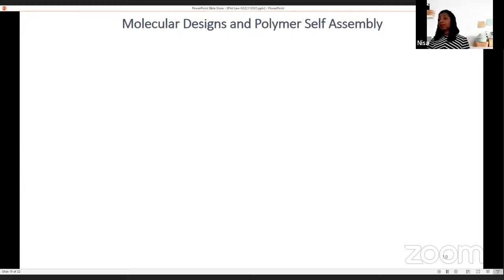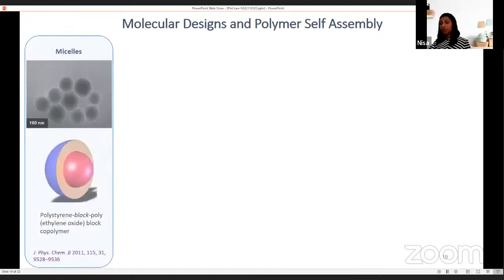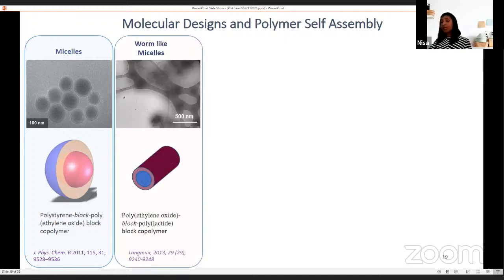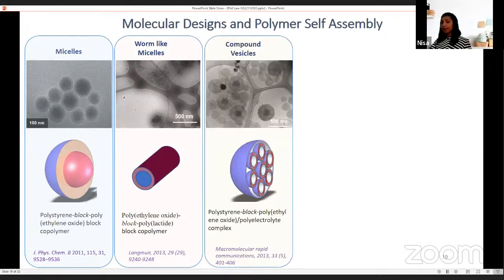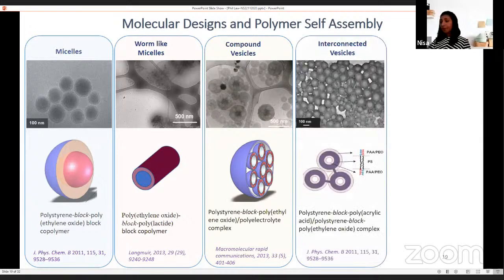I'm going to show you some examples of nanostructures we created in our research using block polymer self-assembly. These are spherical structures formed from a diblock polymer. Here the polystyrene chains form the core and PEO forms the shell. In this study, we came up with very unique thread-like micelles formed by block polymer self-assembly. We also prepared compound vesicles for the first time by using a mix of polymers and polyelectrolyte complexes. As you can see, the structure consists of many tiny vesicles encapsulated inside a giant vesicle. We also prepared interconnected vesicles where you can see the channels connected using polymer chains.